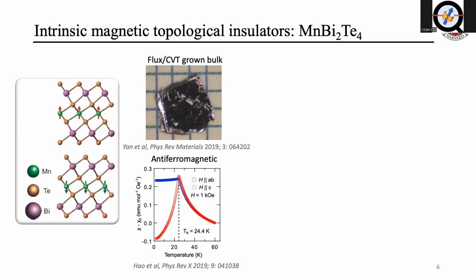So here, this is the bulk sample that was grown by Jiaqiang. In this work the flake is quite large. And as I said, it's an antiferromagnetic material, and the Néel temperature is about 24 Kelvin. It's quite high compared with those extrinsic MTI.